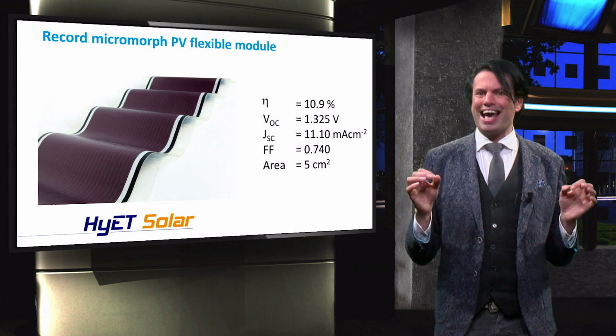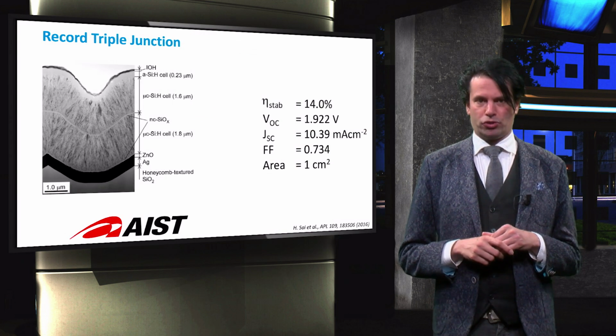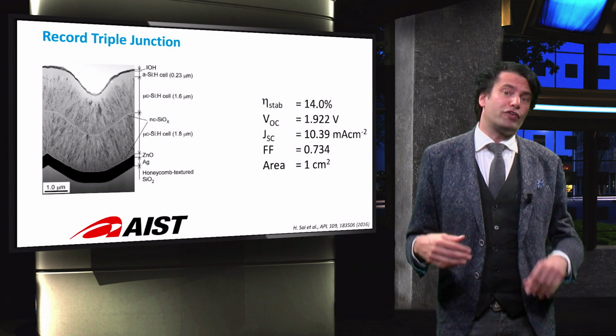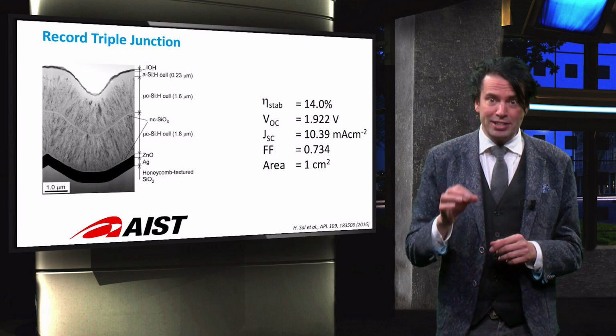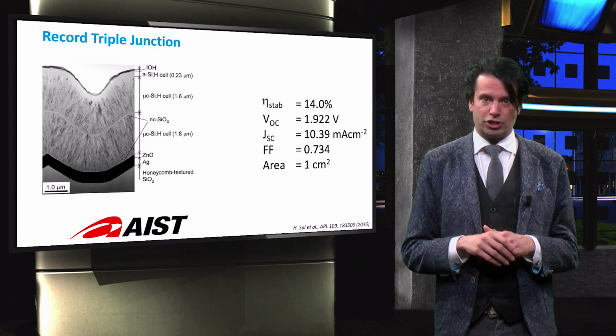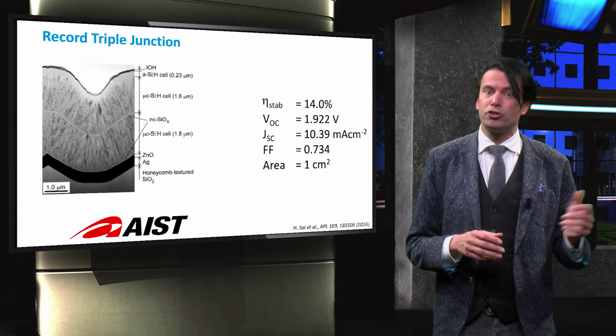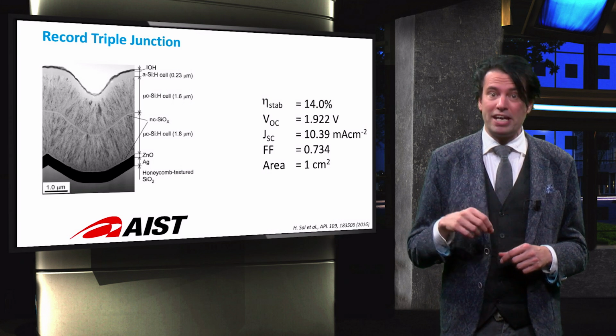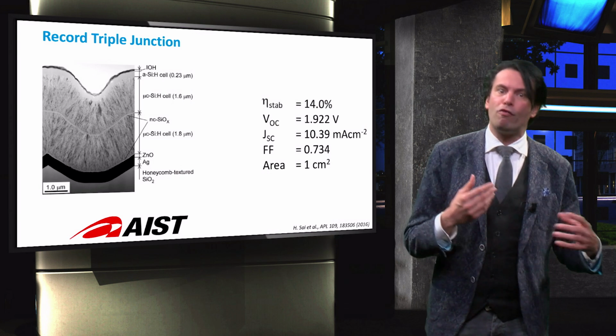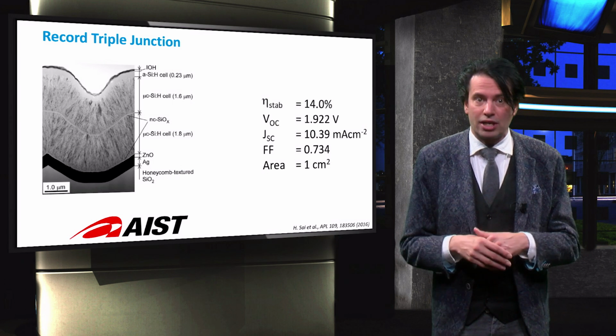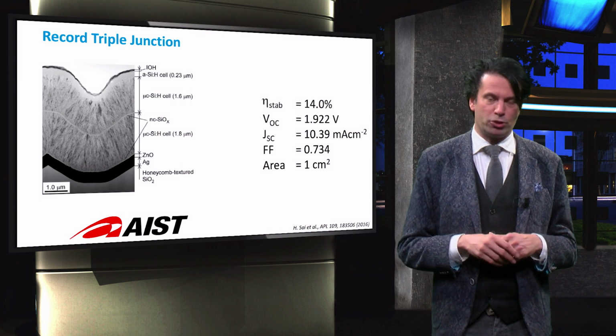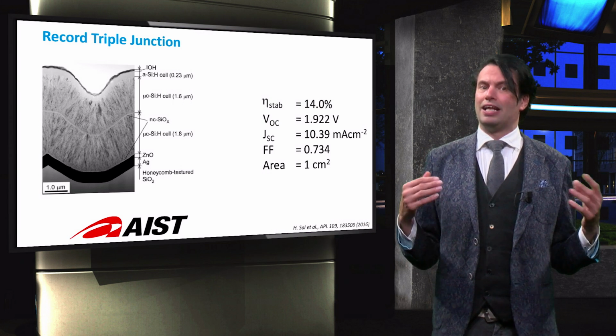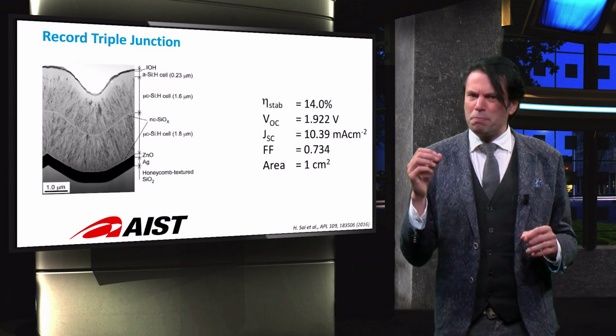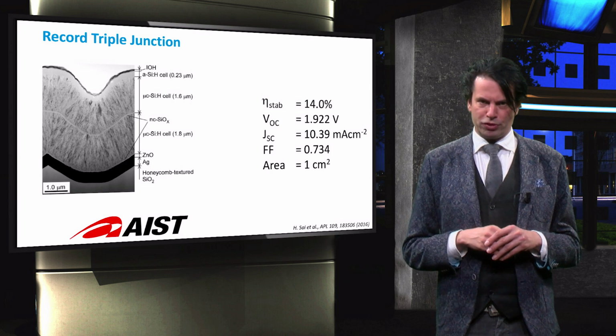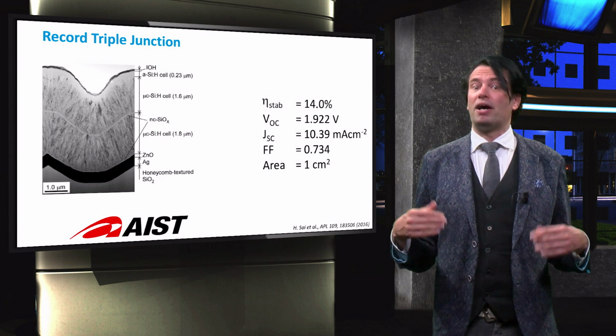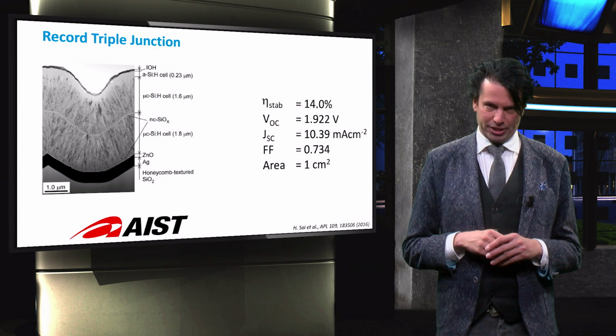Now, let's add one subcell and move to triple junctions. The record conversion efficiency for thin film silicon PV technology has been obtained using the triple junction device architecture. The record was established by researchers at AIST using the substrate NIP structure based on an amorphous silicon top cell and a nanocrystalline silicon based middle and bottom cell. As discussed in the lecture on light-induced degradation, 50% of the power is produced in the top amorphous silicon cell. This cell might partly suffer from light-induced degradation.